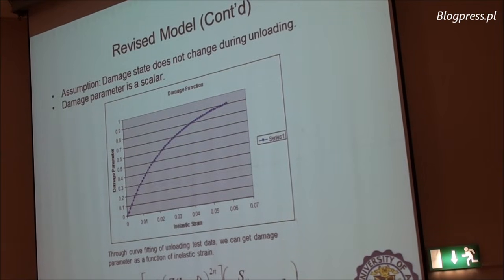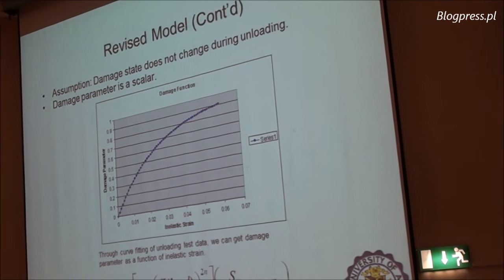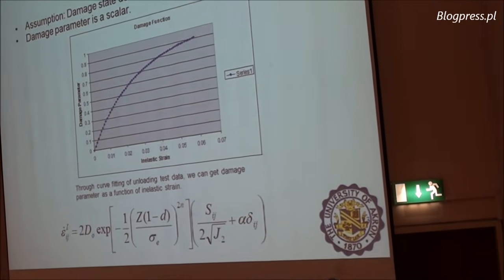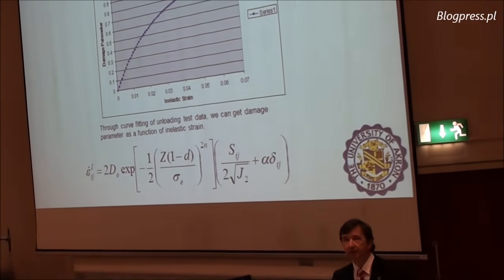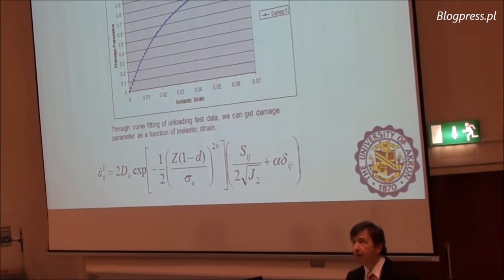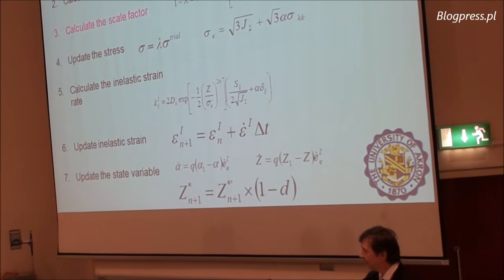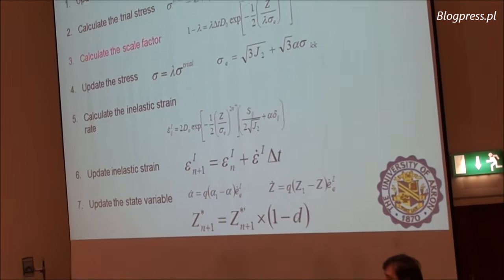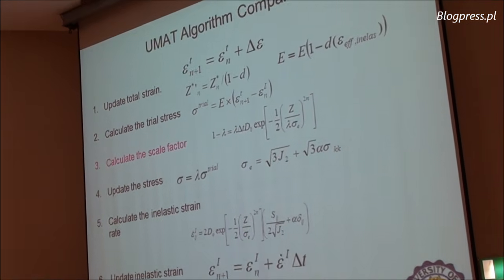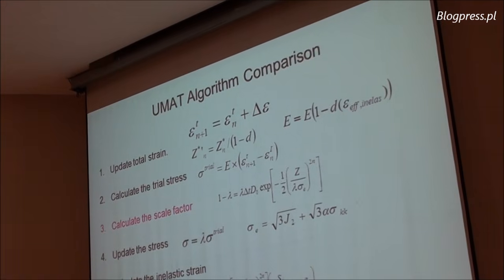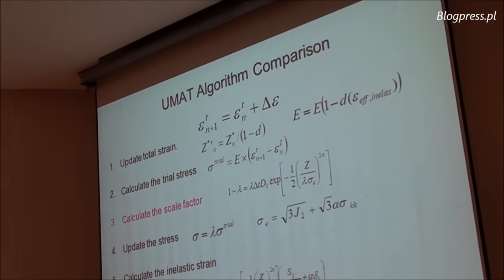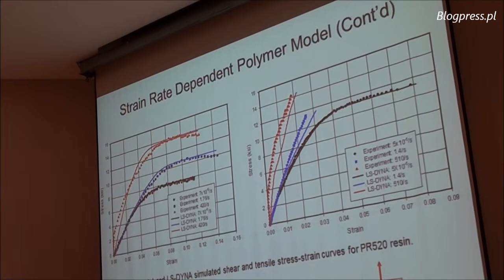The revised model is described here by this equation, where you have effective strain and a damage parameter involved in this equation, and therefore you can have the sensitivity to the behavior of the material, not just as a virgin material as it is new, but also when it is damaged.